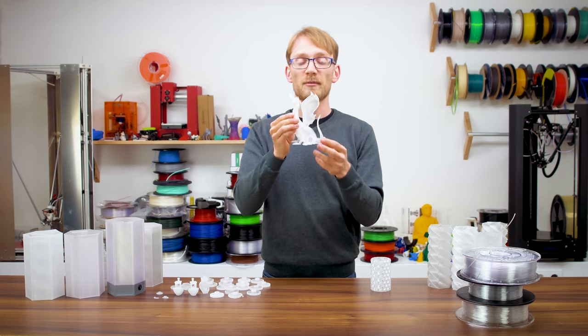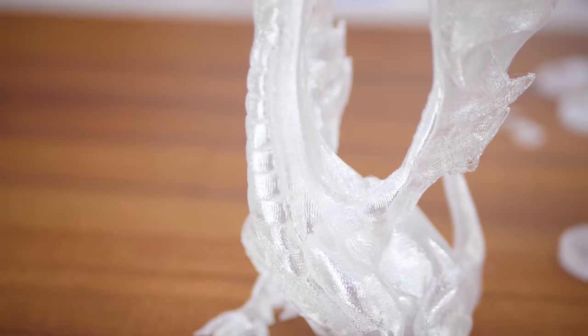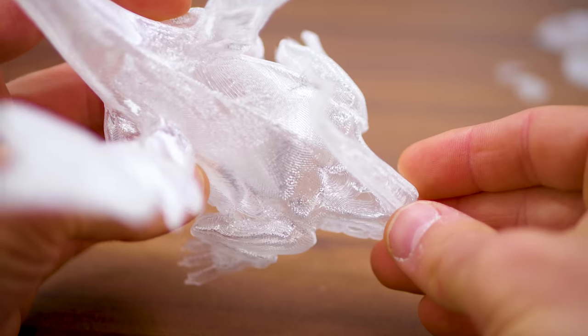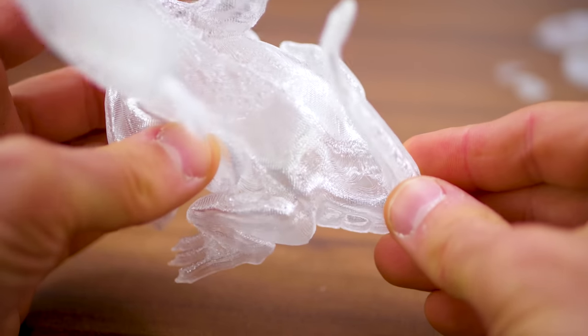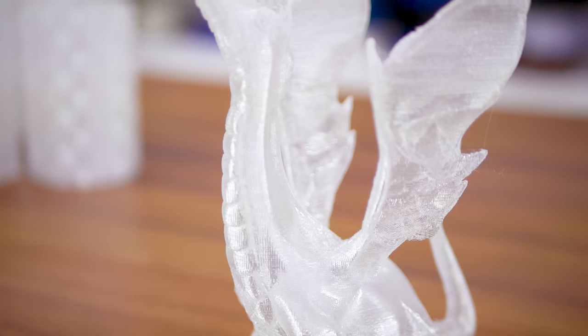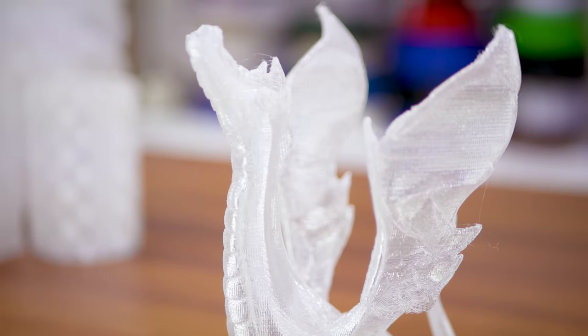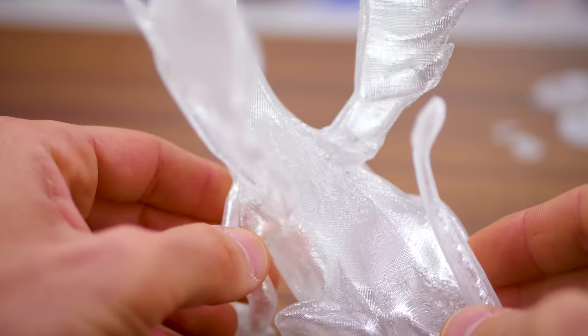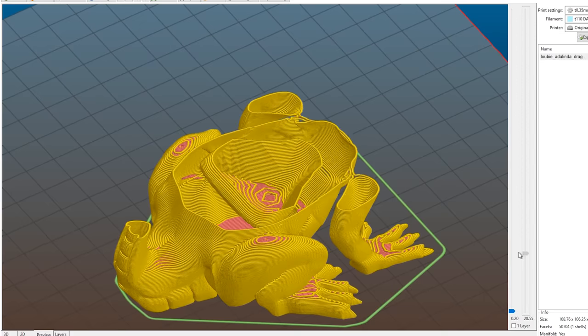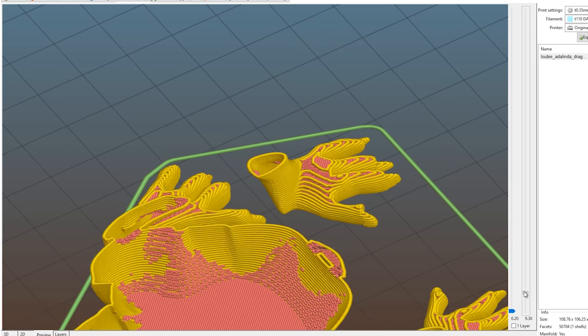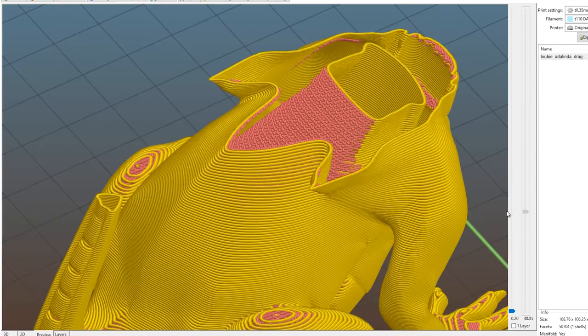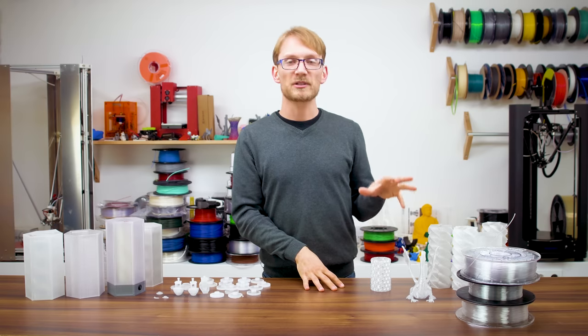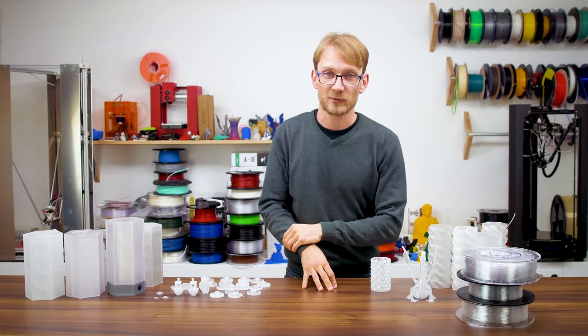But this technique of just using a single wall isn't great for every model. This Adalinda dragon does come out really nice looking with those thick layers, but wherever there's a slope on the surface, the extrusion lines just get super droopy, like on the back, near the tail or on the wings right there. I did configure this print with two solid layers on top and bottom and turned off any feature that would backfill surfaces, which would avoid those exact artifacts, but it would also create these structures on the inside that just don't look great if you see the way they diffract light shining through it. Alternatively, you could print it with a solid infill and thin layers, but that would use up a lot of material and take a long, long time to print.